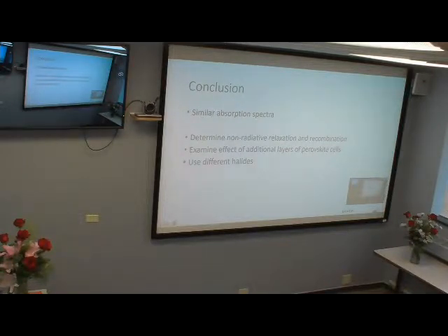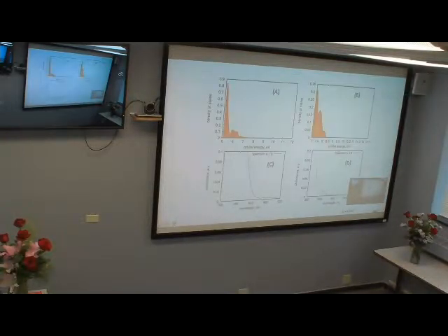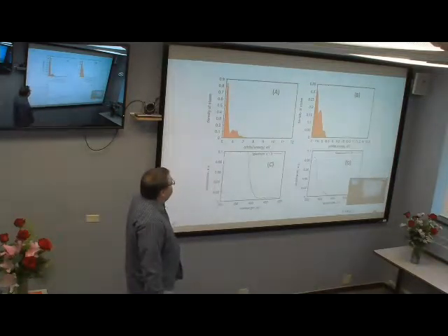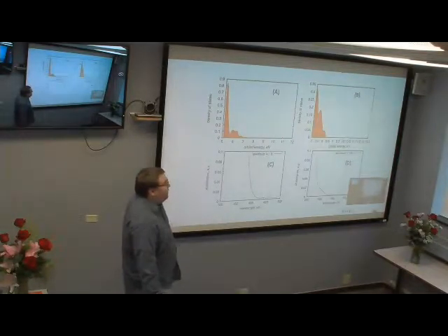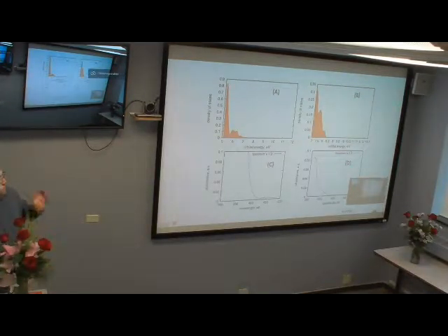Yeah. Can you go back to your density of states? I noticed it looks like B is a larger gap. B does have a larger gap. It was approximately a 2.8 eV gap for the Ruddlesden-Popper phase, where the hybrid had approximately a 2.3 eV gap. What do you think accounted for that change?